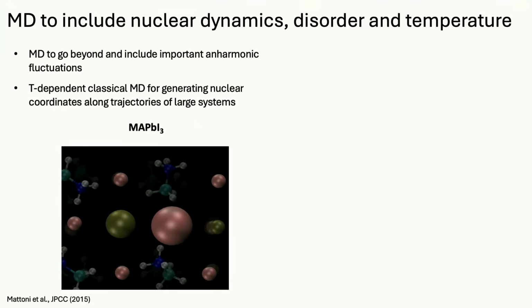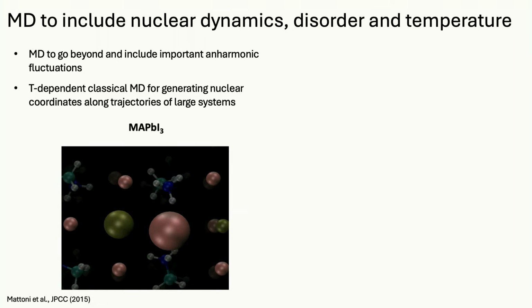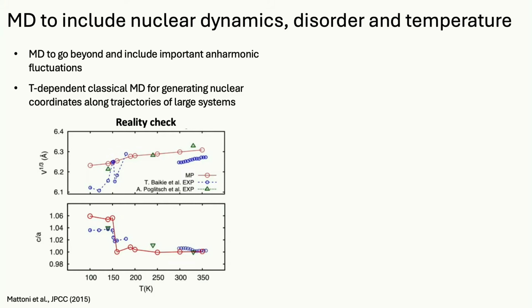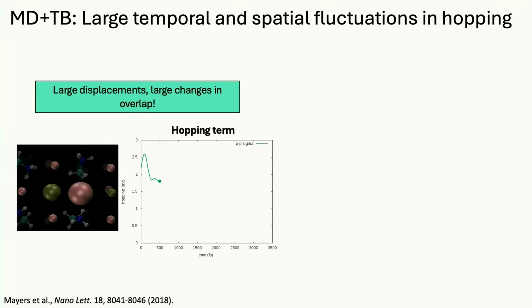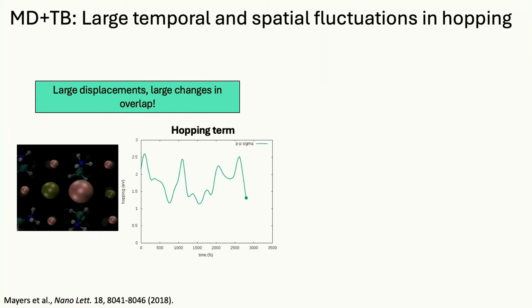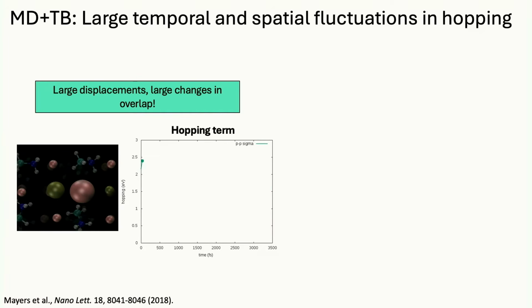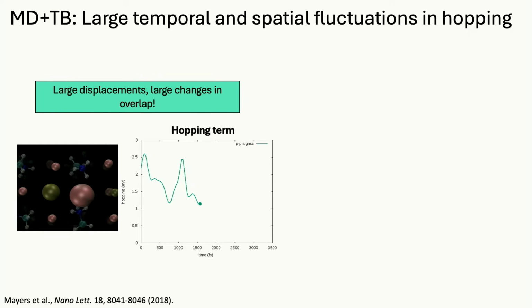So we have this picture of a super dynamic world. Everything is moving wildly, and here, this is the energy for an electron to hop from one site to another. It varies by 100%. Do you see sometimes it's below 1 and sometimes it's above 2.5? And that's on a very short time scale. So think about an electron trying to move through the material. If it's a photovoltaic, the hopping is how the electron gets from here to there, and you get a useful electron. Sometimes it's easy to move, sometimes it's hard to move, and that's fluctuating back and forth on a very fast time scale. So the electrons are dramatically scattered: if they can't go this way, they go another way.